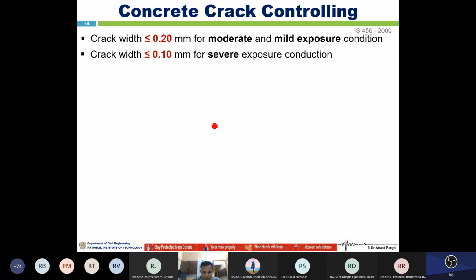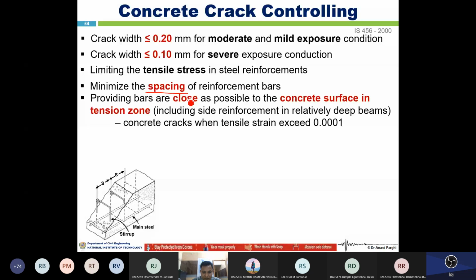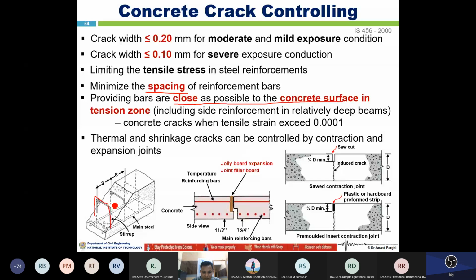So concluding on the crack width, what we have discussed is that it should be less than 0.2 millimeter for moderate to mild exposure conditions, and 0.1 for severe exposure conditions. And how can we limit the tensile stresses in the steel reinforcement, right? Like what we discussed earlier, minimize the spacing, closely spaced reinforcement, and the diameter of the reinforcement should also be smaller. Like here you can see these are the reinforcement patterns, right? The lateral reinforcement spacing should be smaller, so that way you can control the crack.